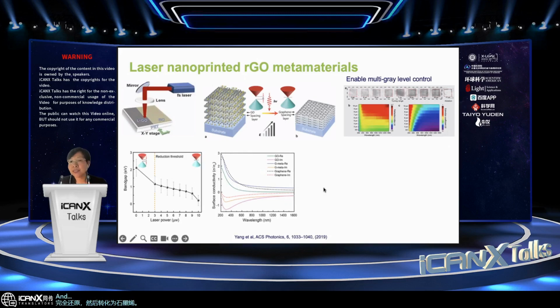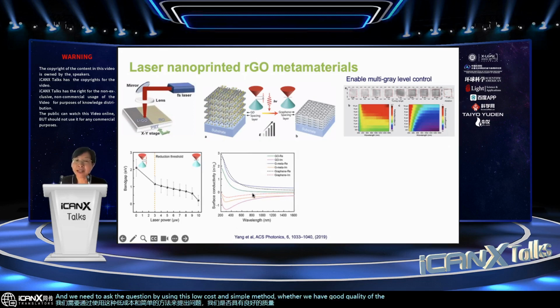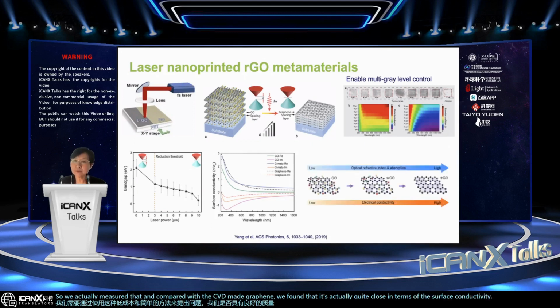And we need to ask the question, by using this low cost and simple method, whether we have good quality of the film. So we measured that and compared with the CVD-made graphene. We found that it's quite close in terms of the surface conductivity. That means the optical property is really close.